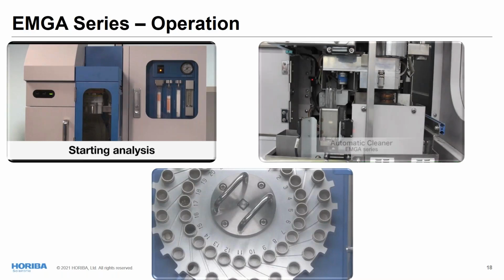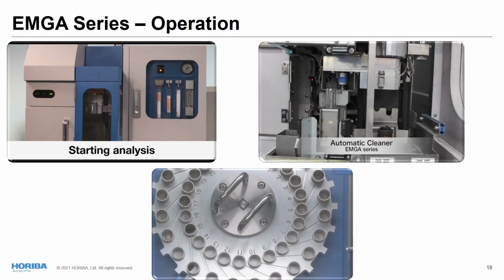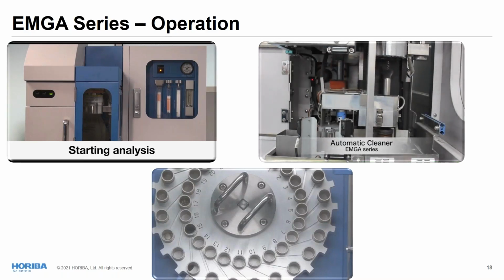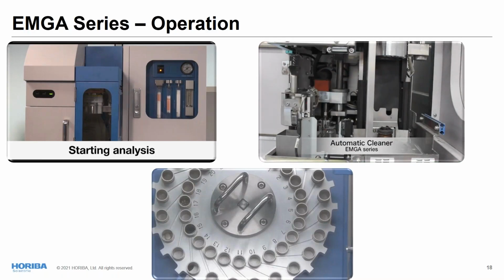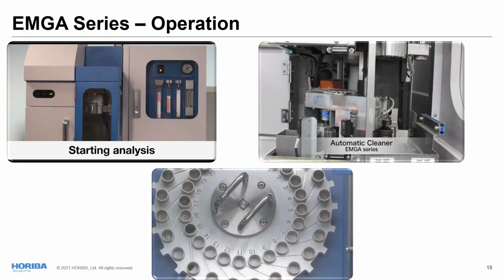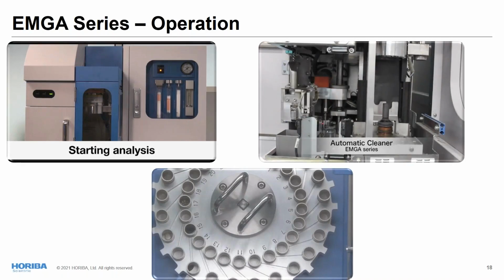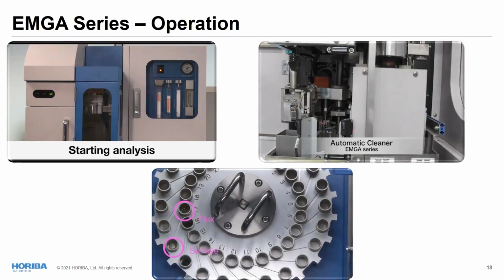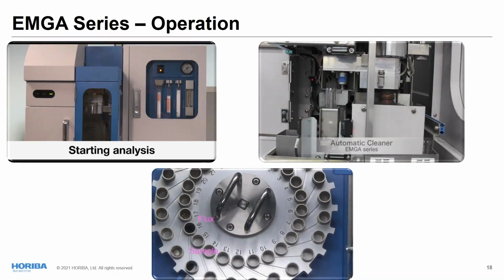Automation is also possible. The system can be equipped with an automatic cleaner and also crucible loader that will be in charge of removing the crucible at the end of the analysis, cleaning the upper and lower electrode, and then taking the next crucible that is happening now on the video. And this next crucible will be installed on the lower electrode so the analysis of the next sample can happen. And again, if you really have a lot of samples to analyze, you can equip the system with an auto-sampler, and it will allow for fully unattended operation.